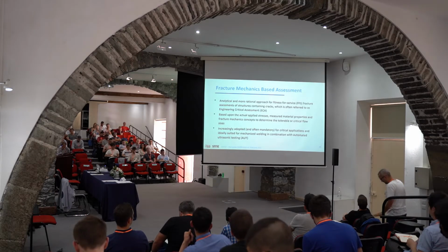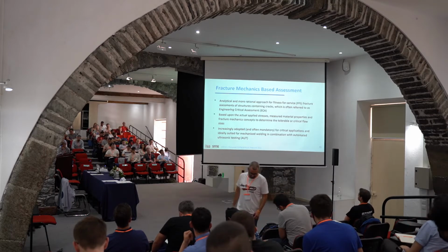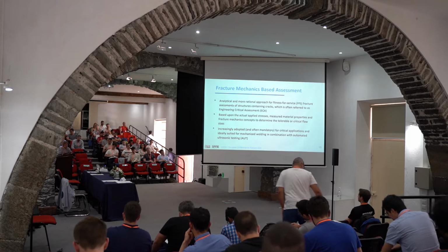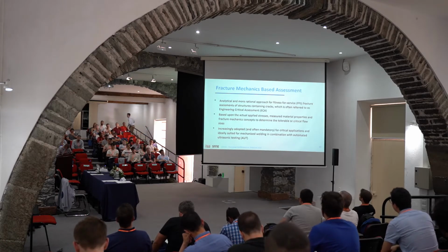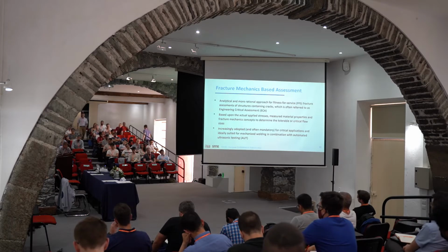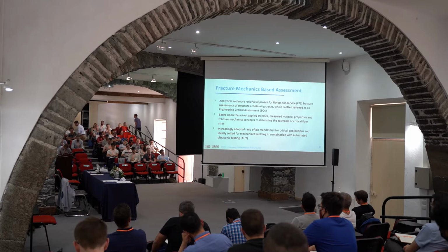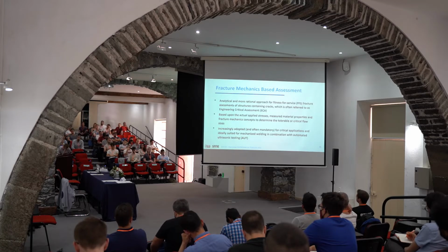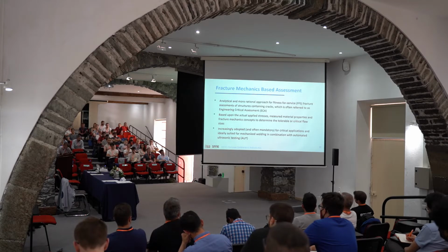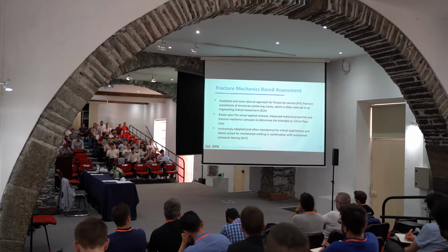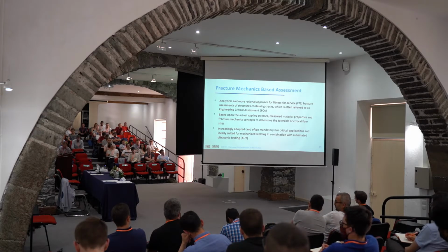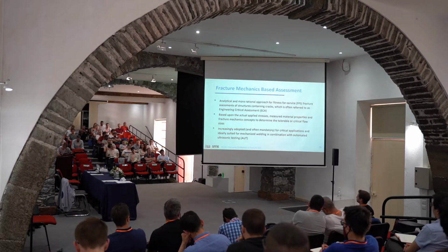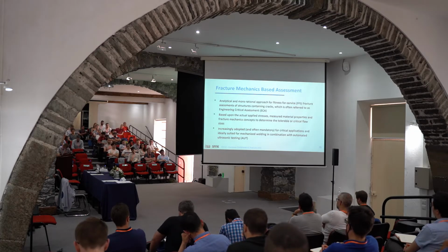Okay? So the basis for the fracture mechanics based assessment is this. Again, fracture mechanics has evolved a great deal of knowledge, especially in the last 30, 40 years. So let's use it. The idea of fitness for service assessment is to use fracture mechanics. And as such, we can use the applied stresses. I can have knowledge of the loading, the actual loading, the remote loading. It's not very easy sometimes, but we can estimate, we can measure, we can quantify the applied stresses. We can also quantify the measured material properties, especially toughness.